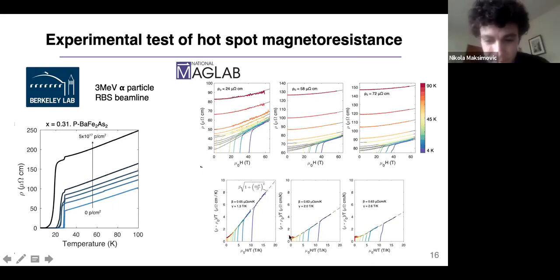I can tell you why this is happening. This is happening because the curvature of these curves is changing slightly. It's actually not perfectly T-linear. So especially in disordered samples, you start to see at high temperature, it kind of has this spoon shape. I can't explain to you why in particular you start to see deviations at high temperature in the context of this model. But it's a reflection of the fact that the temperature-dependent resistivity is changing slightly. Okay. Thank you.